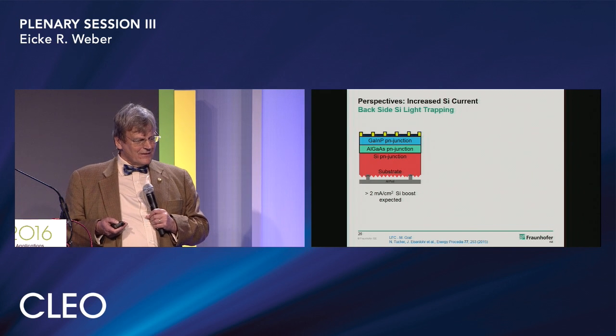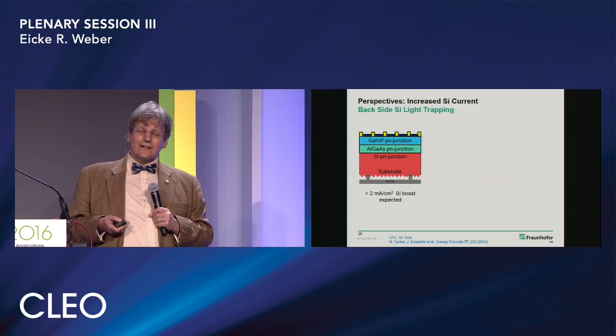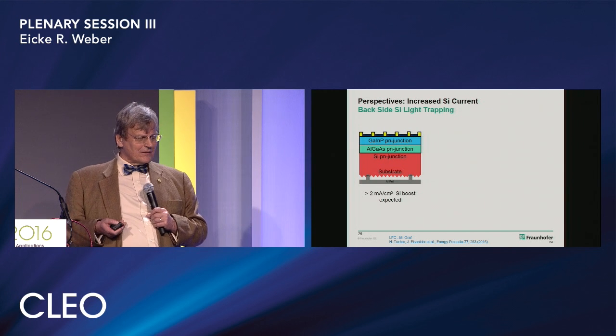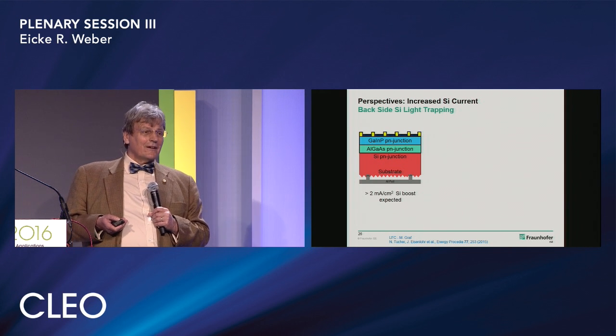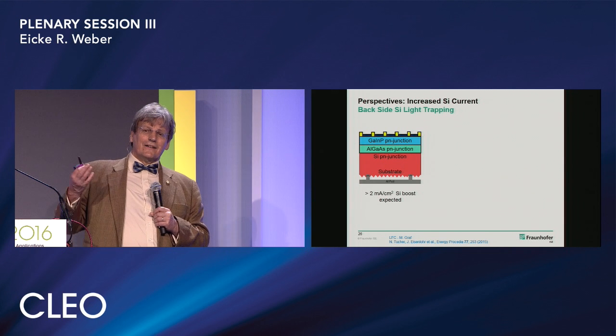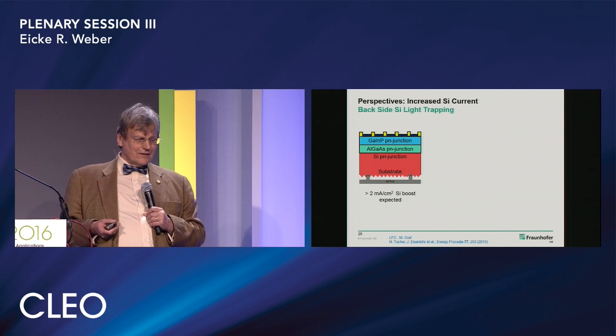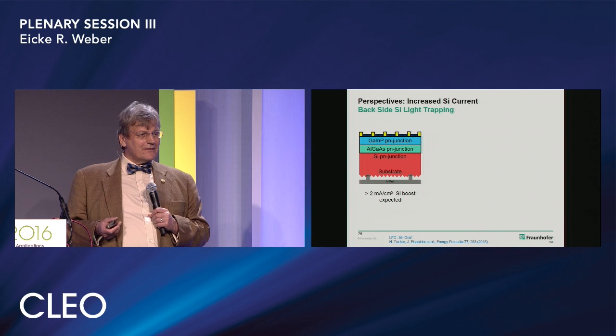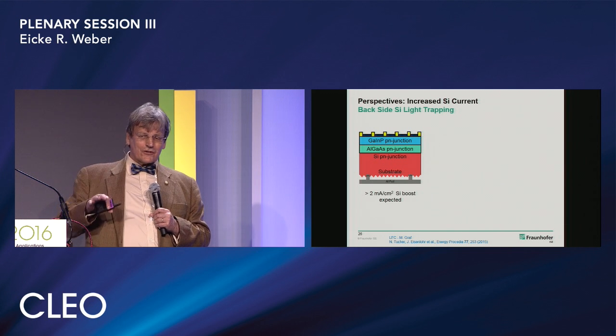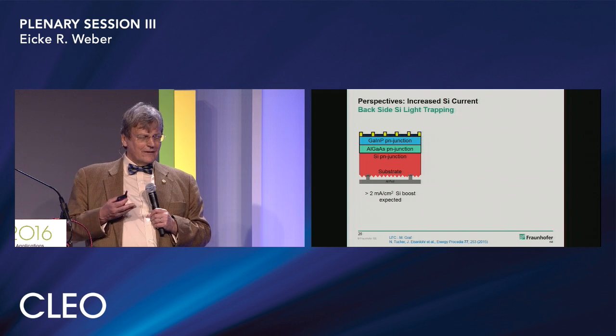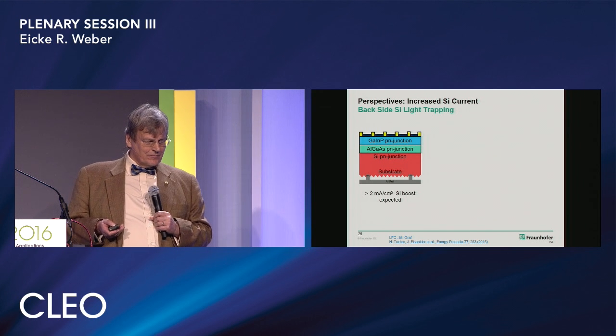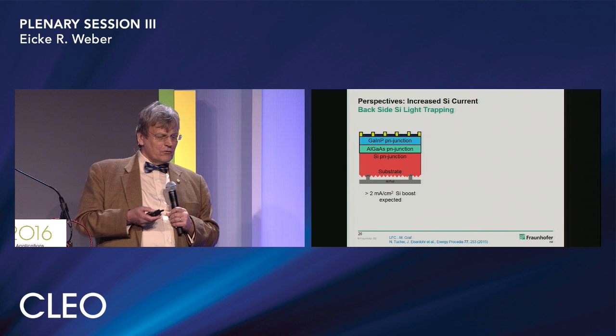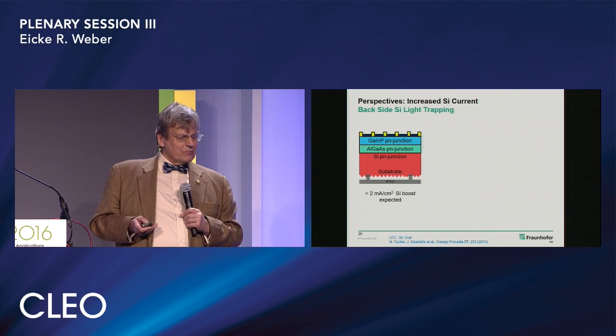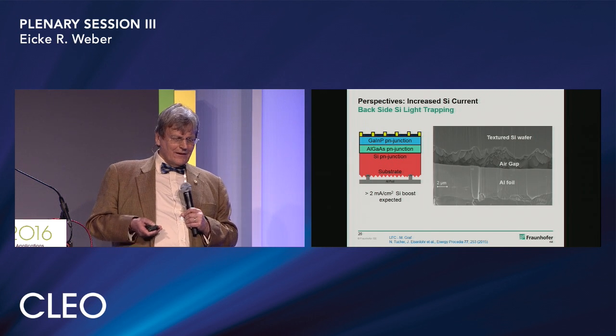And another effect which we can use in silicon and which we have good experience with in silicon is light trapping. In silicon solar cells, the surface is textured so that it effectively traps light and allows through back reflection that the efficiency gets higher than it would be if the surfaces would be just flat. So this gives another 2 milliamps per square centimeter boost in the silicon side. You see here such a textured wafer.